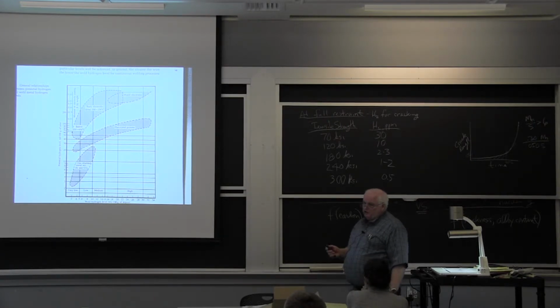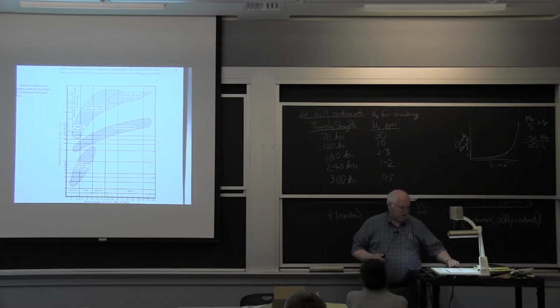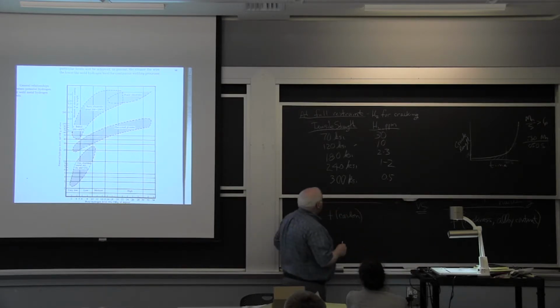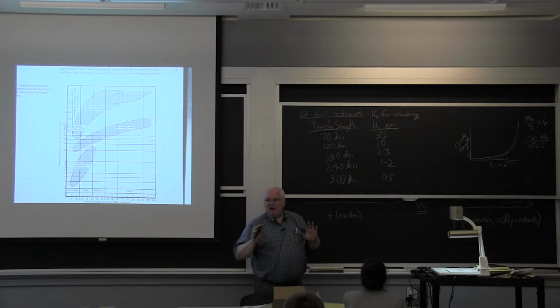We don't use as much stick, but we probably still use it in places that are hard to get to. Well, what does that translate to? A low strength steel, just a 35 KSI yield, which might be a 70 KSI tensile steel, you probably have to have 30 parts per million to crack that. It's very difficult to get hydrogen cracking on a bridge steel or a building steel. You got to really try, and I've tried. I've soaked those electrodes in water and welded with them, and I can't get a hydrogen crack in A36 steel.